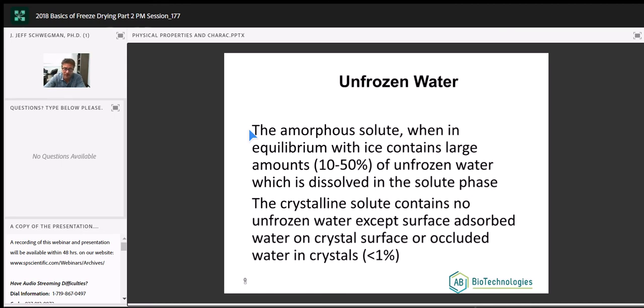However, that's different with an amorphous solid or glassy phase. It actually embeds moisture into that glassy matrix, sometimes up to 10 to 50% of the entire moisture of that formulation. So again, understanding that helps us optimize our secondary drying protocol, knowing how and where water is trapped in our formulation.